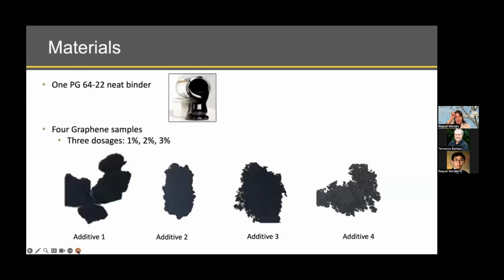The materials evaluated in this study were 1 base binder with a performance grade of 64-22. And we evaluated 4 different graphene products at 3 different dosages, 1, 2, and 3. Here we have an illustration of the products utilized, and we call these additives 1, 2, 3, and 4, so we cannot disclose the product names.